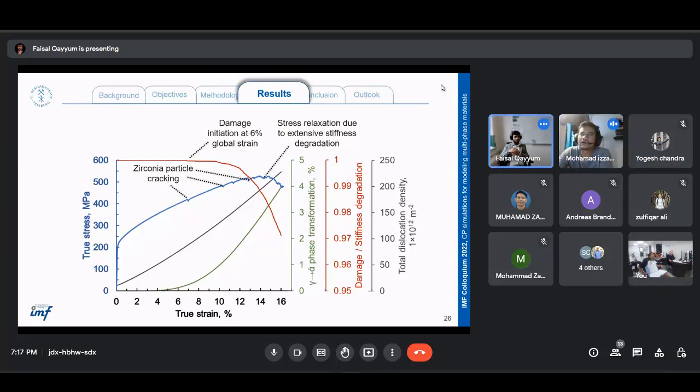For now, no. So you will only consider a single grain? Yeah, but when the grain is changing, we assume that there is a perfect boundary between two elements, so full stresses, and based on the homogenization, the overall boundary conditions and the equilibrium condition can be fully transferred from one element to another without any consideration of the grain boundary here.